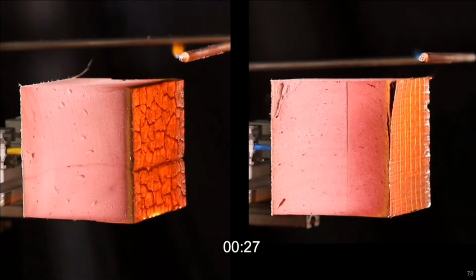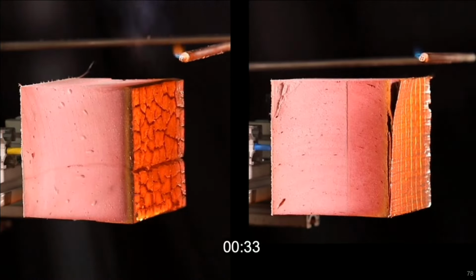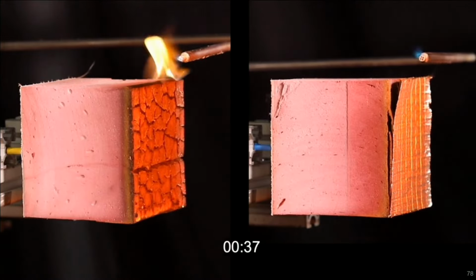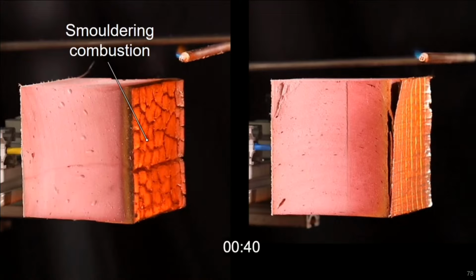The char then begins to glow, and the sample is gradually consumed by smoldering and a physical loss of material from the foam's surface. And once this has stopped and I've pointed to the glowing, I'll let the experiment run at 40 times its normal speed. So you remember that the RS5000 did not glow like this.